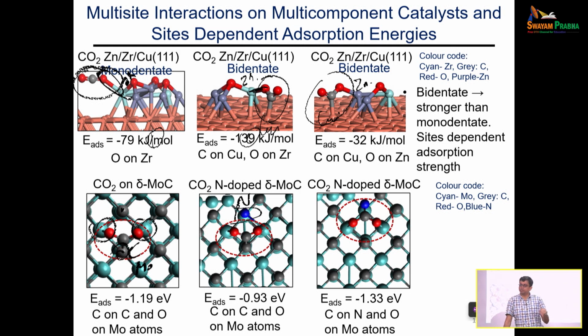Even if the adsorption does not happen on the impurity, its presence, that's what this particular middle panel shows, right? Even the mere presence on the surface changes adsorption energy so much. And what I would say is catalysis and adsorption requires you to understand the surface of your material to an atomistic scale for you to be able to comprehend what is happening in the measurements that you are making.